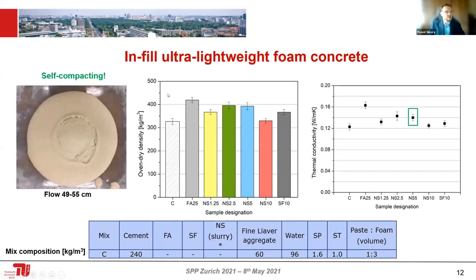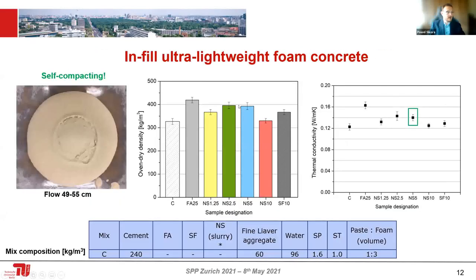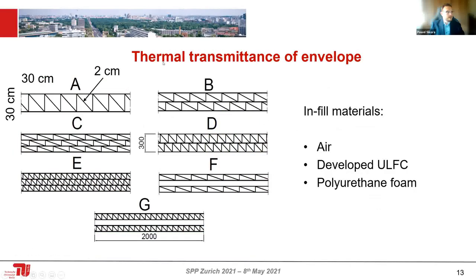Now going to the opposite challenge: since I produced the 3D printable material, I now need to fill it with an ultra-lightweight infill concrete. For this purpose I need a self-compacting material that flows very easily inside. I have developed mixtures with a thermal conductivity of 0.14, which is three to four times lower than the load-bearing element, and with density five to six times lower than conventional concrete. Here you can see the different topologies I have analyzed — these are theoretical wall configurations that can be printed.